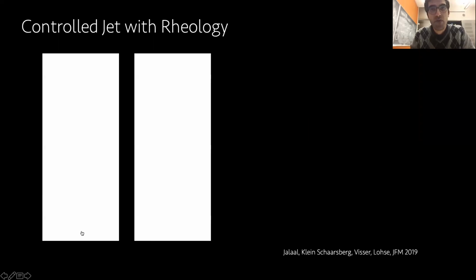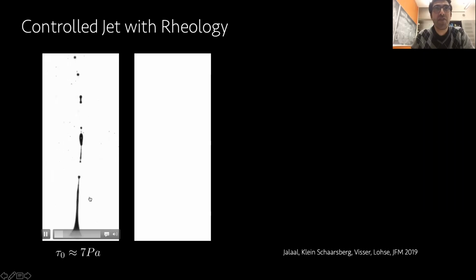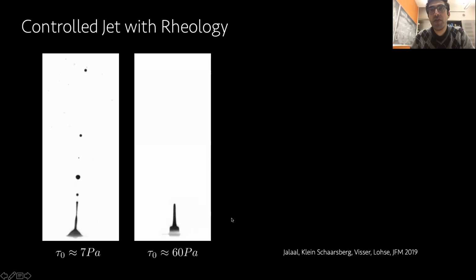Okay, so we controlled this jet. This is what happens. Everything is the same in these two videos I'm going to show you, except the yield stress, the rheology. So this is low yield stress. Everything is splashing around. You don't want to print with such a jet because there's a lot of residue. But if you tune your rheology with a little bit of Carbopol, for instance, you can get this very nice jet. So this is perfect.